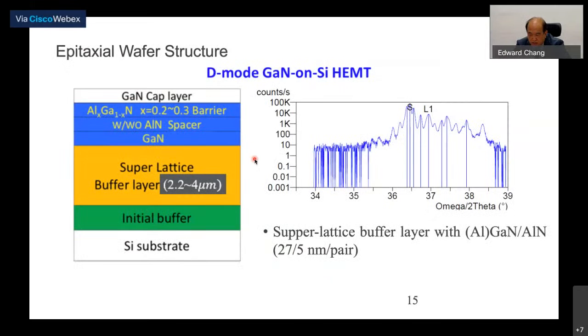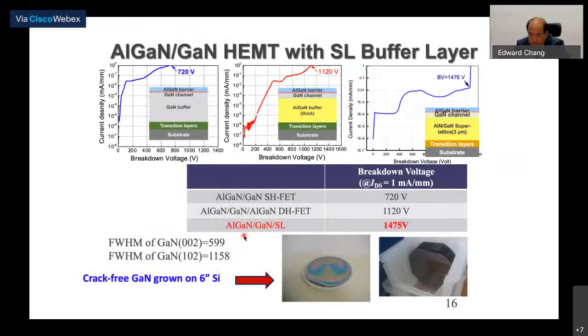So this is the typical structure we use for D-mode devices, okay, with gallium nitride cap, and then AlGaN with aluminum nitride spacer, and we use superlattice buffer with some carbon doping, okay. So this is the typical performance: if we use AlGaN, it is 700 volts, and if we use double heterojunction, we can get up to 1100 volts, and if we add the superlattice to it, we can get up to 1500 volts.